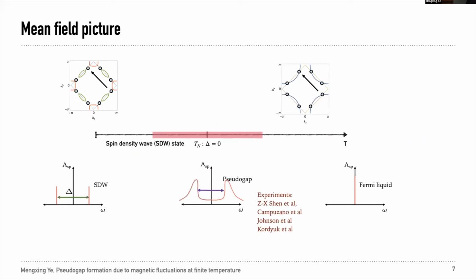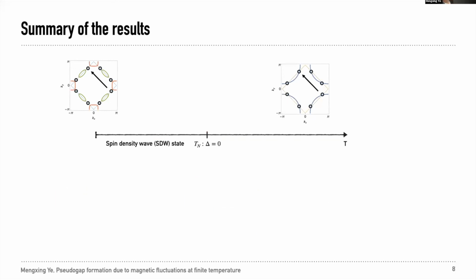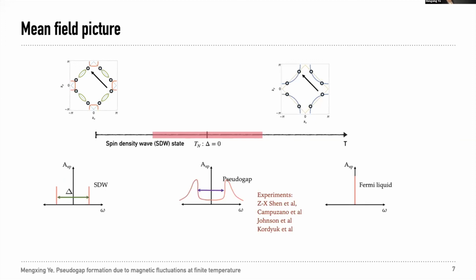Okay, so to begin, let me first tell you about what we would expect from a simple mean field picture. Let's start at high temperature, where this right panel shows the Fermi surface in this blue curve. And as temperature decreases, the system starts to develop spin density wave at momentum q equals (pi, pi). We can see this tendency by looking at the spectral function at these hot spots, where on the Fermi liquid side, it's peaked at zero frequency. And as soon as the order starts to develop, the spectral function is gapped at these hot spots, where this gap is determined by the SDW order parameter.